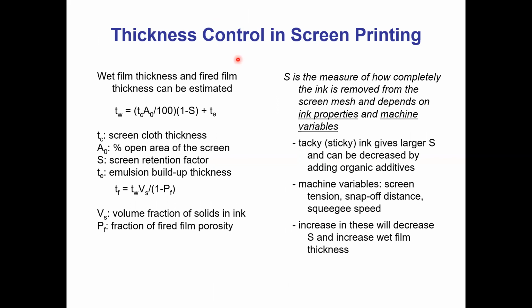I talked also about the connection or correlation between the wet thickness versus final fired thickness, and you can do some modeling or you can do some analysis. So the thickness of the wet film is given by this equation, where this is the thickness of the emulsion. That is, if you are using a patterned screen, there is a certain thickness of emulsion on the screen, and that's that. If you don't have any emulsion, you can take this out. The other parameters that control the wet thickness depends on screen cloth thickness that is known, percent open area that is known, and the screen retention factor that is controlled by both machine variables as well as property of the ink.